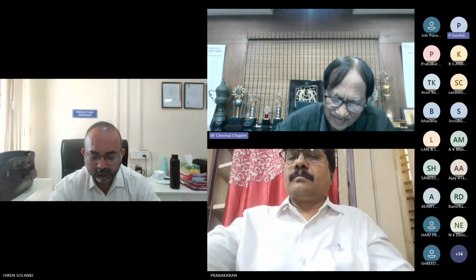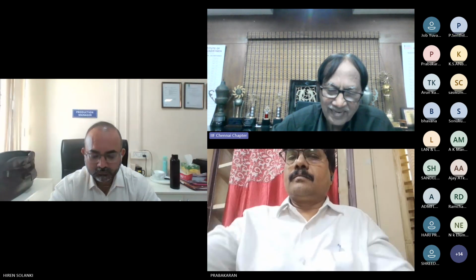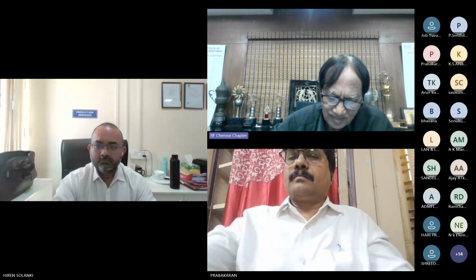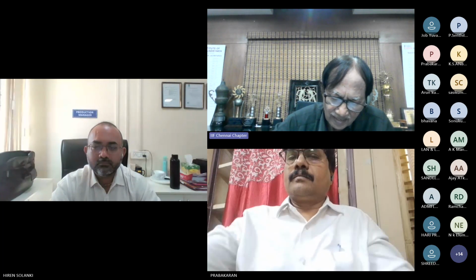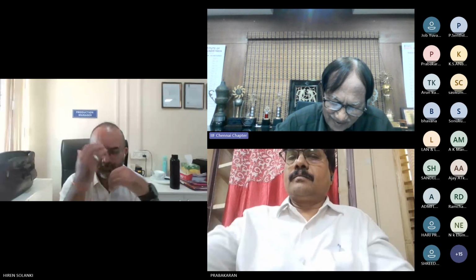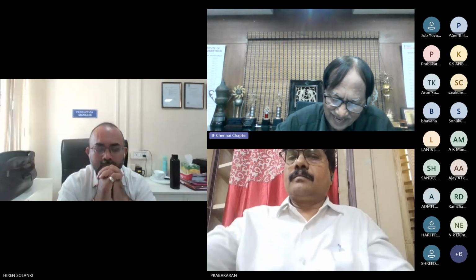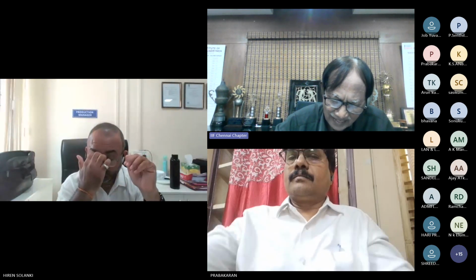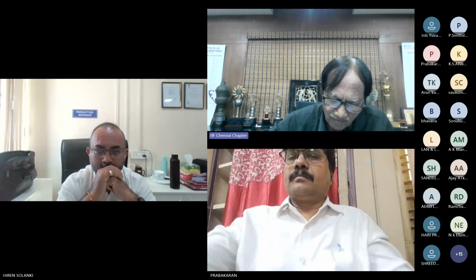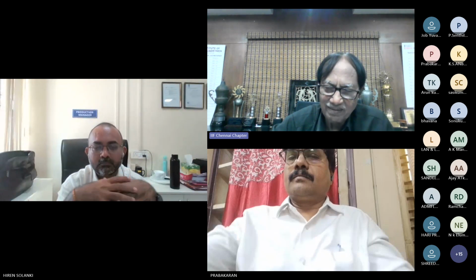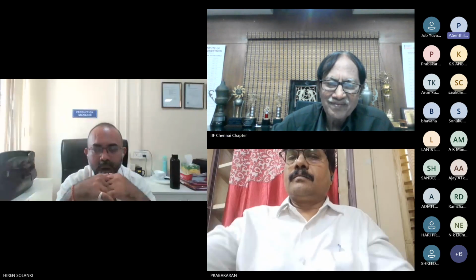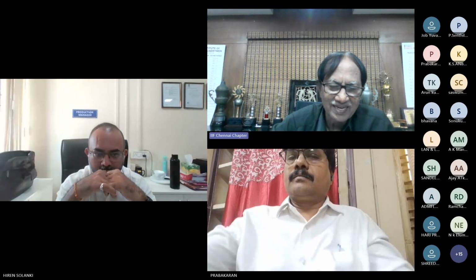They put up a chart and there is a continuous recording of the metal temperature. They get very good castings, and they follow tilting gravity casting. But unlike in India, the degassing time is 45 minutes. You may not agree or believe it. Here we do it only for 10 or 15 minutes. I asked why 45 minutes; they want to take out the micro inclusions with the fluxes, and the transfer rails are preheated.